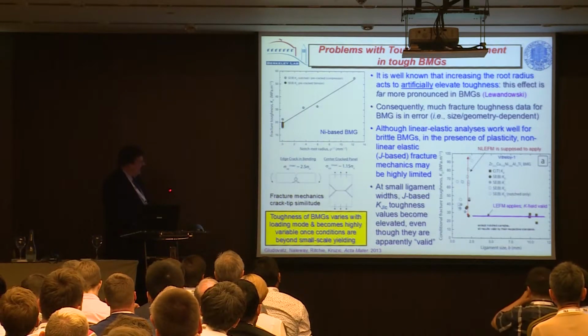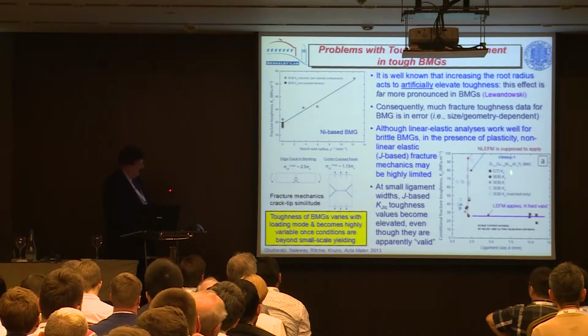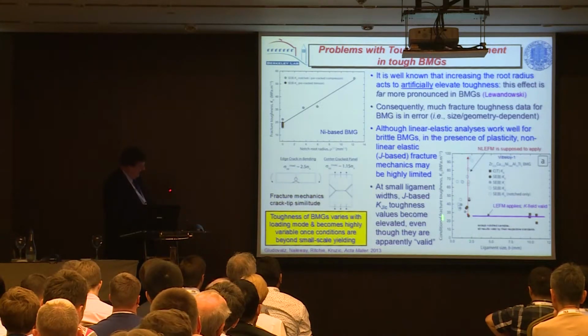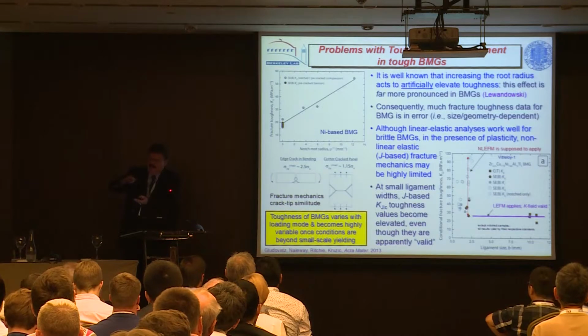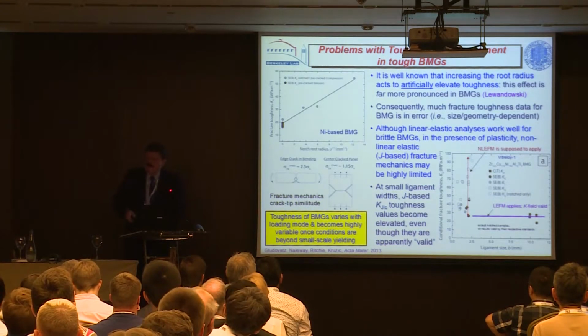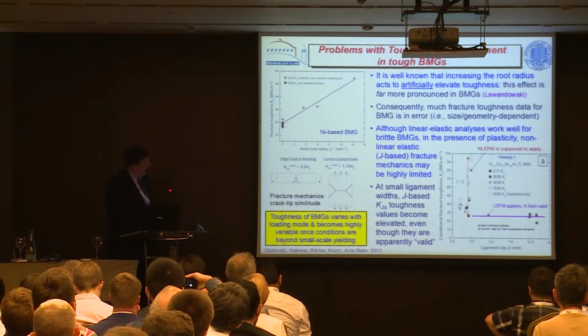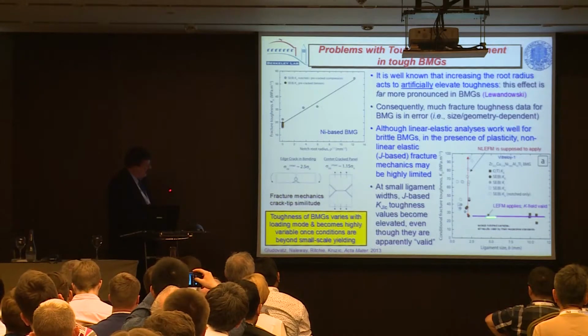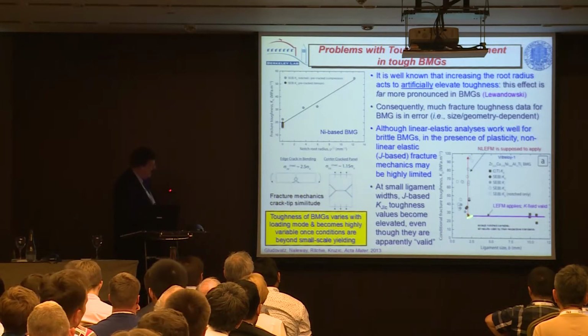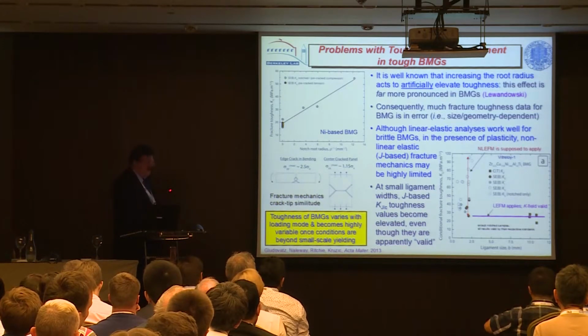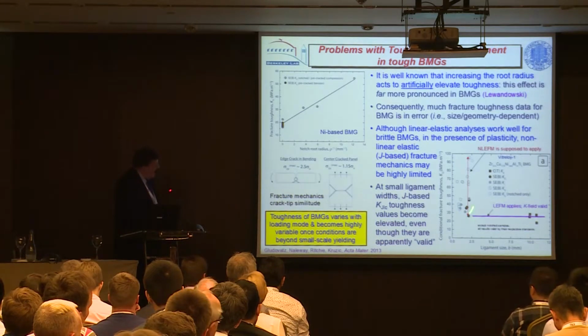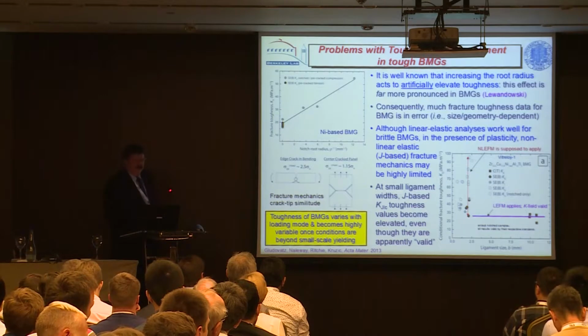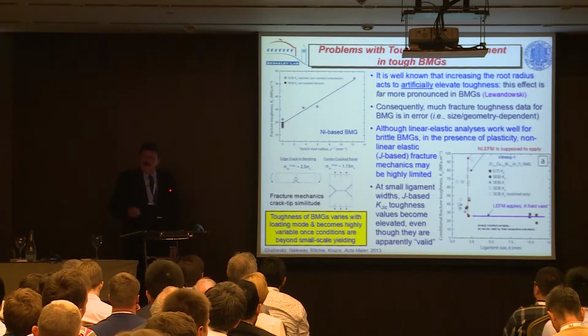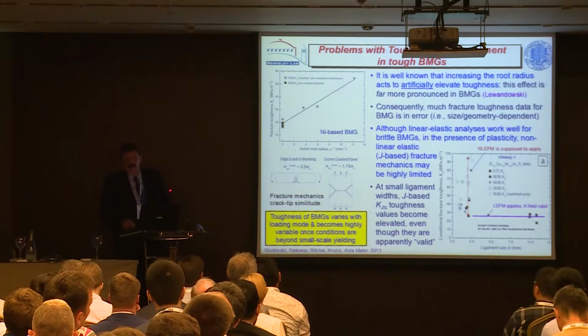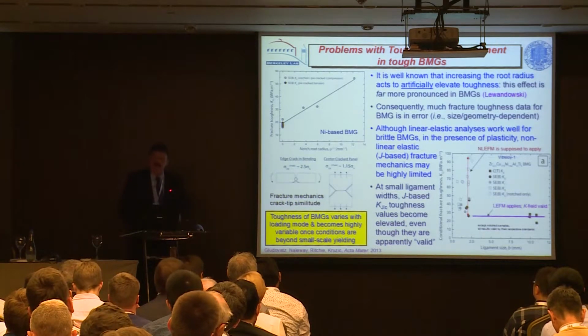But if you measure it properly, and we try to measure it properly, this is looking at quite a common glass, Vitreloy 1 again. This is the toughness as a function of the ligament size. This is basically the size of the sample. This pertains to small-scale yielding, whether you have a K field or not. If you're measuring in a linear elastic regime, in the relatively less tough glasses, everything's fine. The toughness, as you might expect in a crystalline material, doesn't vary with the size of the sample. But as soon as you get out of that regime into the so-called non-linear elastic fracture mechanics regime, where J should apply, instead of getting a number in terms of J, which is constant, you just get this massive scatter in the data. And this is, as I said, almost an order of magnitude in the variation in toughness.